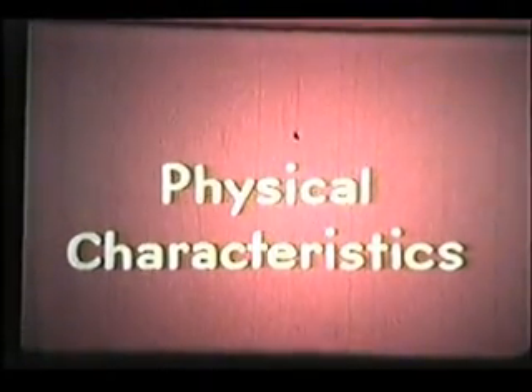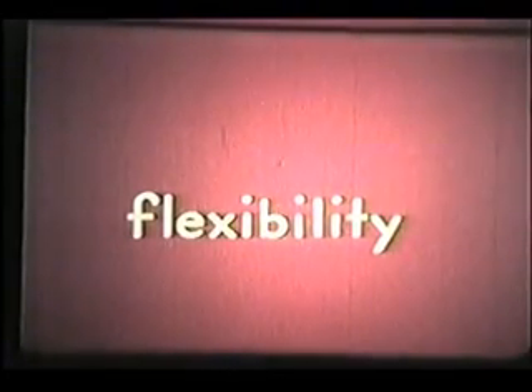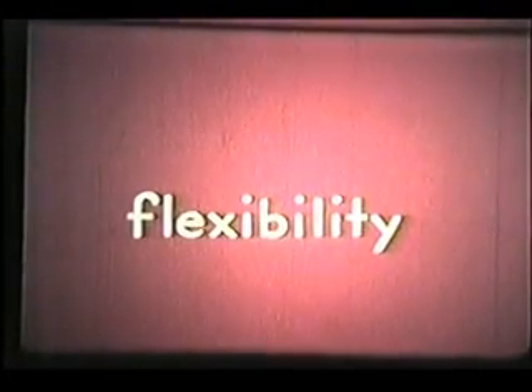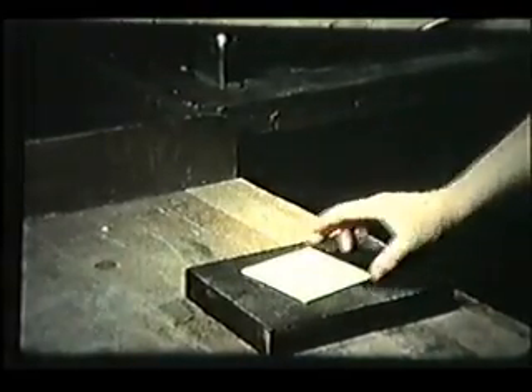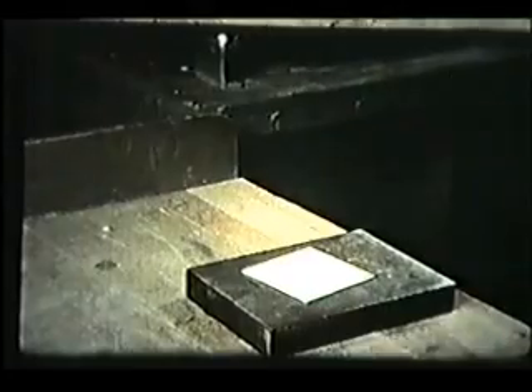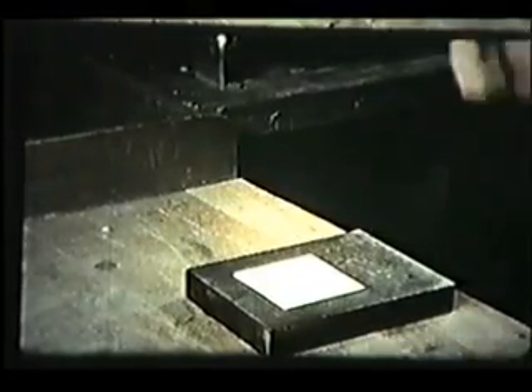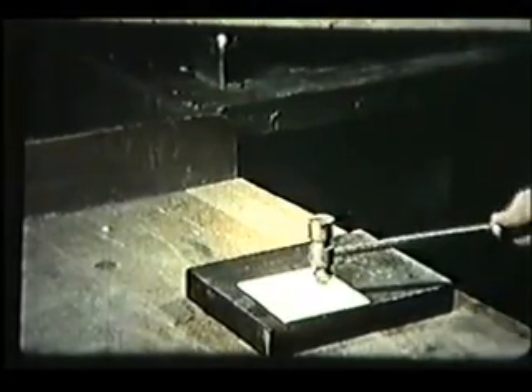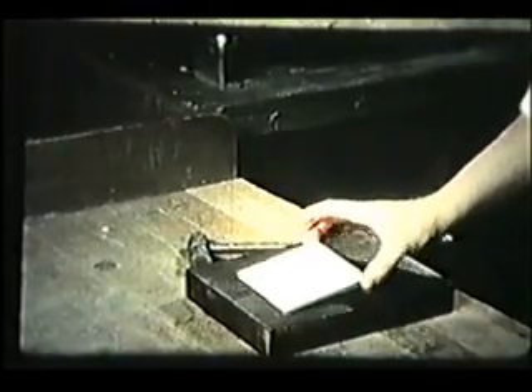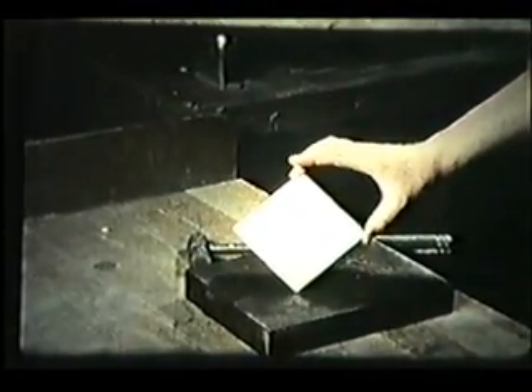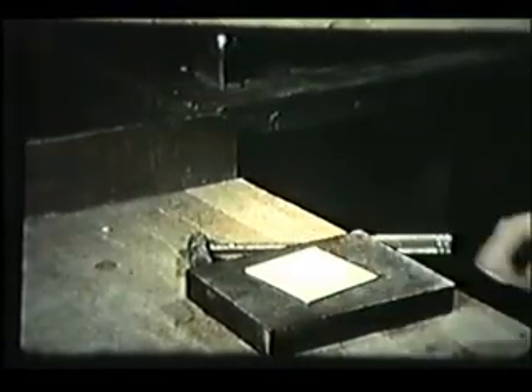One of the predominant features of Rokide is its flexibility. Thin coatings alone can flex like paper. By flexing with the base material, Rokide withstands substantial vibration and distortion without loss of adhesion. Here the coatings are being abused to demonstrate their ability to conform to the distortion of the base metal when subjected to the action of a ball-peen hammer. Although it is somewhat difficult to see, all that has occurred is a slight powdering of the coating at the surface where it conforms to the indentation of the hammer.